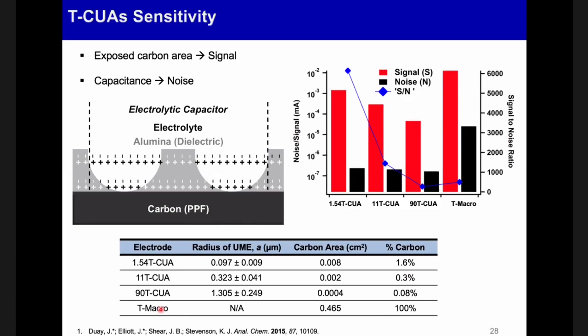Actually, the biofouling on this platform has been amazing, which I know a lot of the other electrochemistry sensors for this is a big issue that they see. However, on our platform, we have over 10,000 electrodes in this area that we work with, and most of it is dominated by this aluminum oxide layer. If you look at the current responses in just the buffer around the experiments, before the 48-hour experiments and after, they're almost identical. We can't really see differences. So that's been a very good indication of the biocompatibility. That's a really important thing because you can have the best electrode in the world, but if you can only use it once or twice, it's still okay, but it's not great.